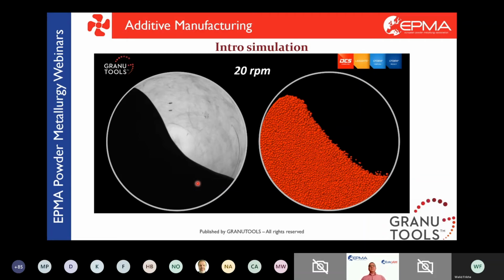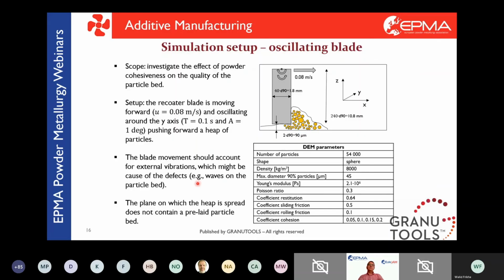And since the drum is a proxy to the recoating process, so we have the same process conditions, if you want to do a simulation on spreadability, then you can, and you will get very good results. So this is what we did here.